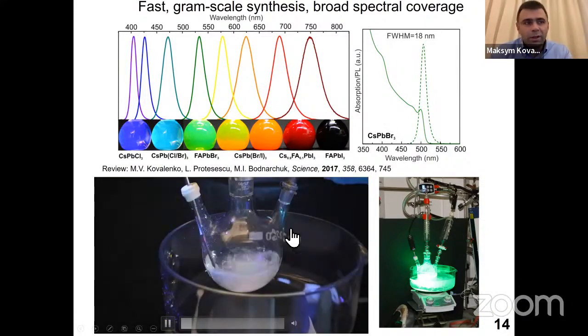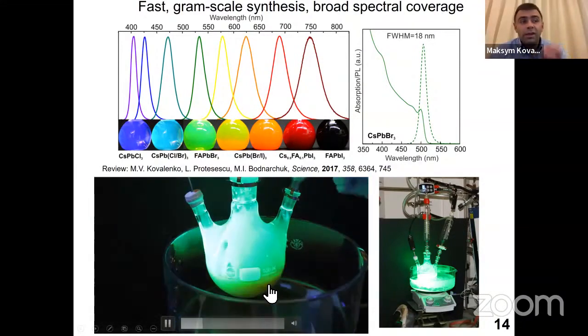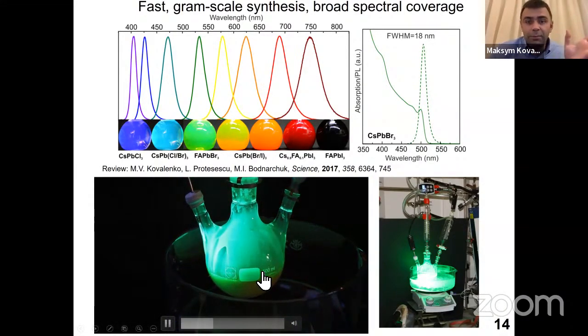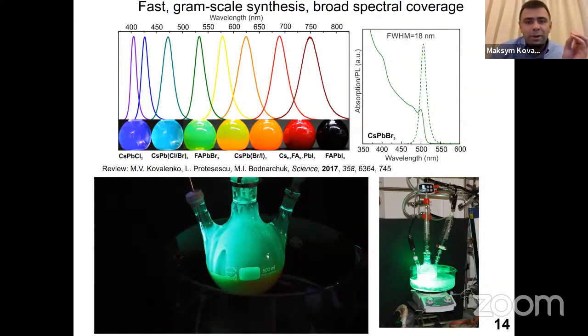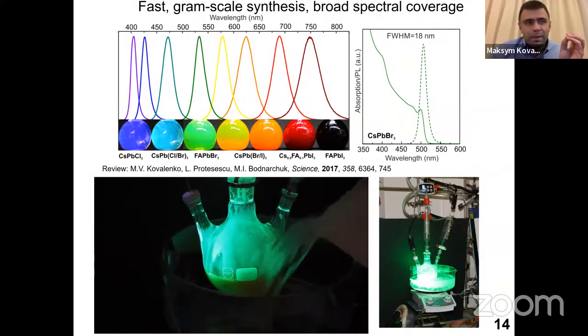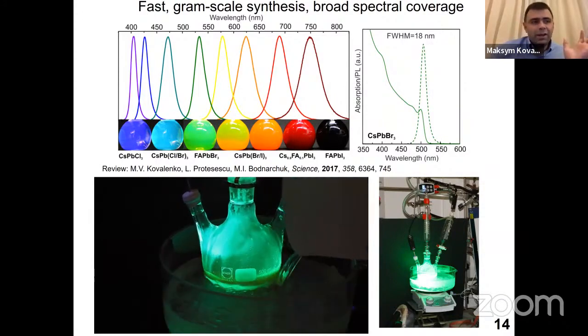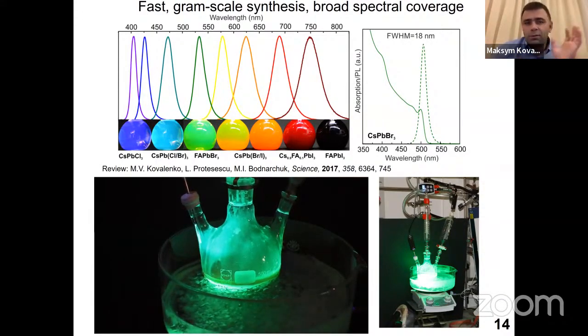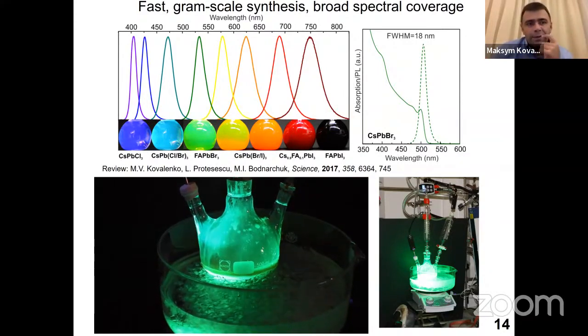Before you understand the problem, let me show you how the synthesis looks. You inject cesium oleate into lead bromide solution, and you see immediate appearance of quantum dots. They are green emitters. So the reaction is completed within the mixing rate, which looks very exciting, right? So you very quickly can produce grams or kilograms of these quantum dots. At the same time, such a fast reaction is a problem if you want to have very fine control of the size, especially down to very small sizes, or if you want to grow some heterostructures and so forth.